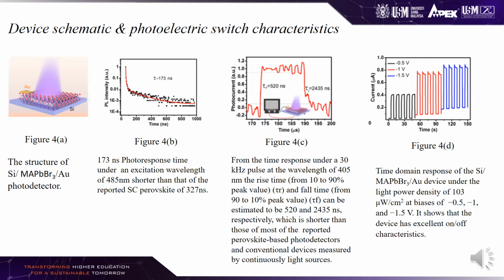From the time response under a 30 kHz pulse at the wavelength of 405 nanometers, the rise time from 10 to 90% peak value and fall time from 90 to 10% peak value can be estimated to be 520 and 2435 nanoseconds respectively, which is shorter than those of most of the reported perovskite-based photodetectors and conventional devices measured by continuous light sources, shown in figure 4c.